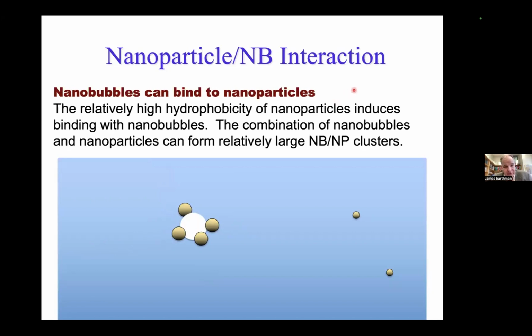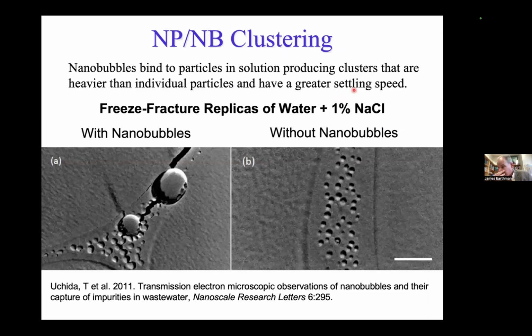Now, these particles may not be stable. They may be embryos. They could be at the solubility limit of this solid, and they could just be forming and dissolving over time. But if they bind to a nanobubble, their surface tension is going to go down, and they're going to become stable. And if we keep doing that, we can force the concentration of that solid to below the solubility limit.